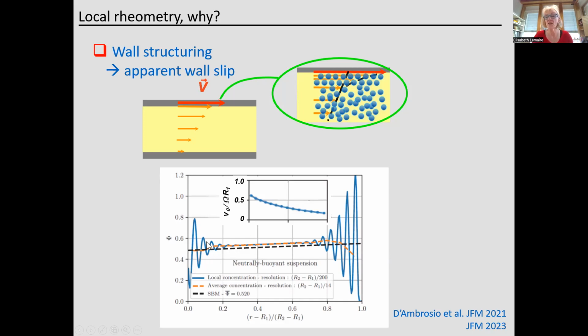And so here you can see results obtained in our group by Enzo D'Ambrosio. And here you can see the variation of the particle volume fraction in a wide gap Couette cell. And you observe that near the rotor and near the stator, you have a huge layering of the particles. And if we measure the velocity field, then we observe a very important wall slip. Here, the velocity should be 1, and the velocity is only 0.6. And it's almost the same near the stator.